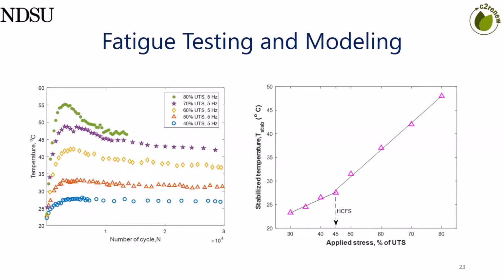What I can say in general is these biocomposites that we've developed have that break-in period that you see with any type of advanced composite structure. Look at fiberglass reinforced softball bats, for instance. There's a sweet spot where they have a break-in period where you have to damage the structure to a certain degree, on the very micro level, to get the ultimate performance of that material. Then after a long period of time or number of cycles, the performance starts to tail off due to the repeated impact of that structure. We see several similarities with natural fiber composites as well.